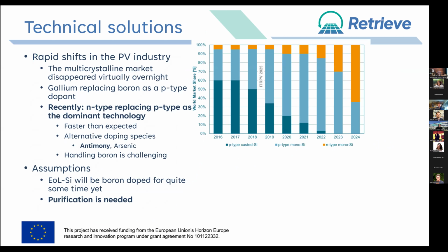And we have seen the last few years some really rapid changes in the market. Multicrystalline wafers disappeared in a couple of months in 2019, I think. Gallium replaced boron as the p-type dopant of choice virtually overnight. Right now, we are seeing a change from p-type technology to n-type technology. And when these changes kick in, it always happens faster than expected. And even now in n-type technology, we're seeing some tests with alternative dopings with, for instance, antimony. So it means that, again, the material we are recycling, 15-year-old material, is not the same as they're using in silicon and in solar cell production right now.